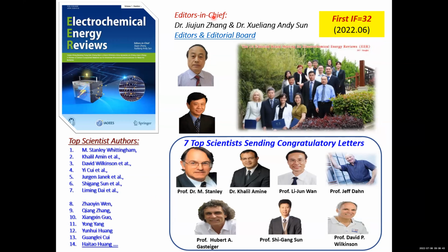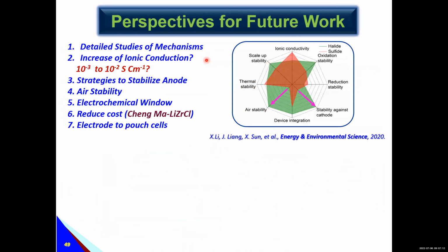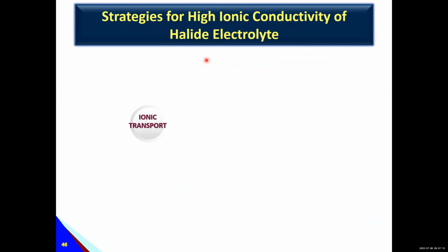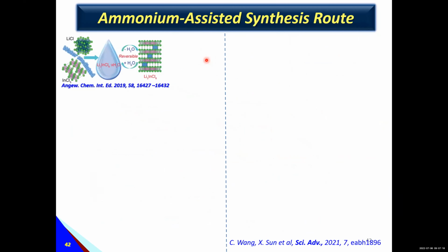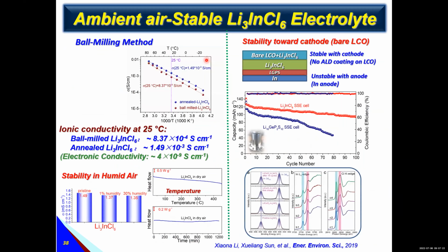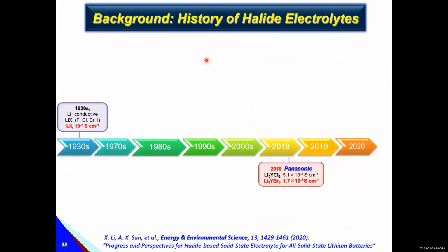Maybe I'll start by asking the first question. In the first part of your talk, you used ALD to put a coating on the cathode particles. For a battery using liquid electrolyte, there is a tendency to use large single crystal particles. But in a solid state battery, if you use your ALD technology, do you imply that you don't have to use very large single crystals? You can use relatively smaller primary particles and coat them with ALD, and they can also provide good performance.